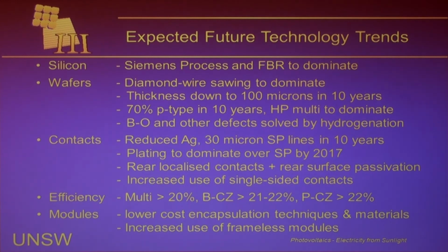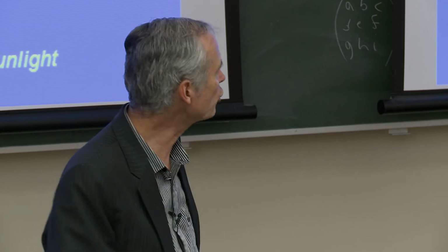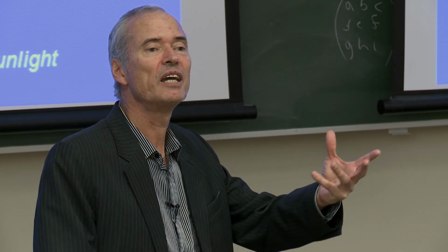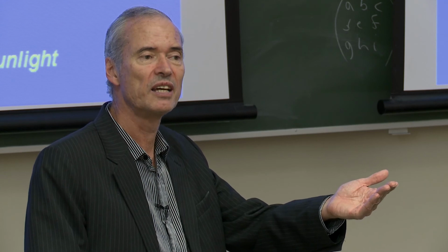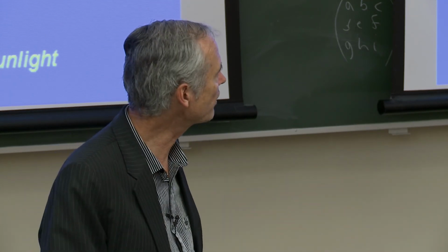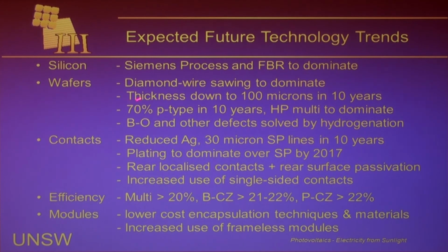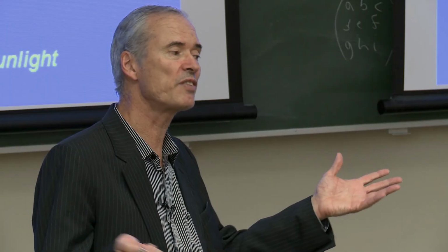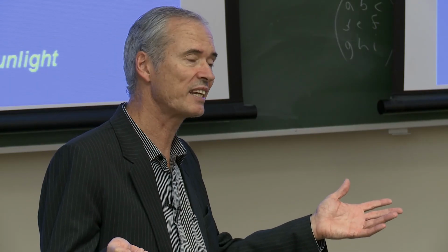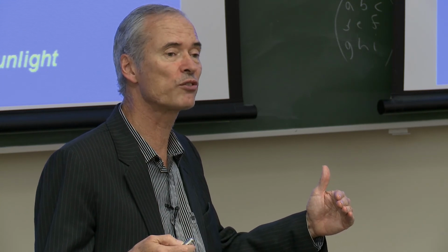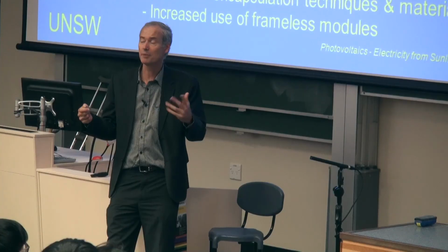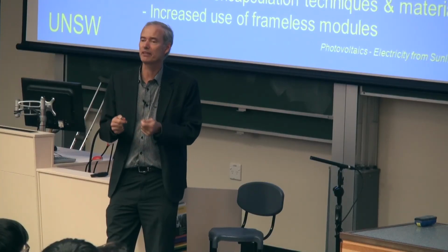Then we have the wafers. So once you've got the silicon, you then need to turn it to the right crystallographic form. So you normally melt the silicon and then you crystallize it. There's a range of ways you can do that, and we're seeing some evolution in the techniques used, techniques that are able to help bring down the cost. One of the things that's happening is that the thickness of the silicon wafers is being reduced. Obviously, if you make them thinner, you use less silicon, so it's cheaper. Also, by making it thinner, you don't actually sacrifice any of the efficiency of the solar cell. The main problem is that by making it thinner, you can break them more easily.